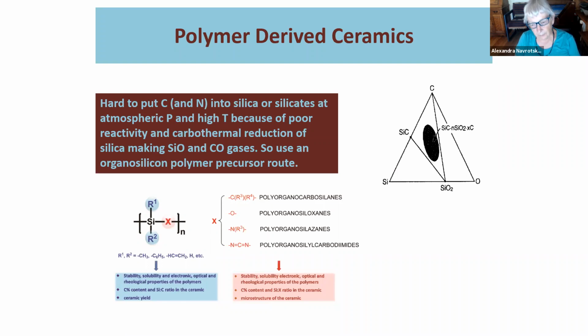into these polymer-derived ceramics. And the main notion then is that you take organic groups, you tailor them for the amount of silicon-carbon bonds they have, silicon-oxygen bonds, amount of carbon, amount of nitrogen, and then you carefully pyrolyze them, and the pyrolysis goes through a number of stages, and the final product is then your so-called polymer-derived ceramic that contains carbon that is part of the ceramic structure, and that's what we've been working on. And again, the tie-in with fibers and so on is that you can, of course, make fibers of these materials, and they have certain advantages and disadvantages compared to, say, silicon carbide fibers.